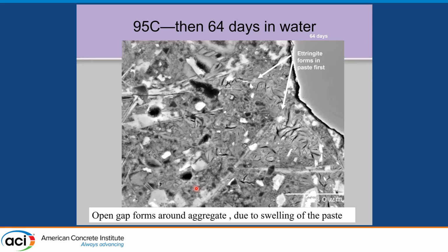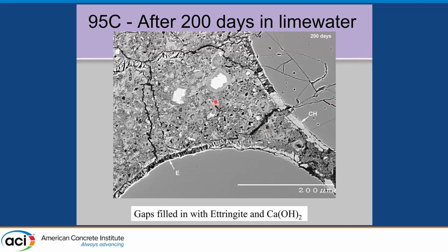And what happens then, when that sulfate comes out of the CSH, you start to form this delayed ettringite in very small spaces within the paste matrix. You see these little tiger stripe pattern things are ettringite that's formed in the paste. The other thing you notice here is this is a sand grain in the upper right, that the gap there is empty. So when the expansion occurs, the paste is expanding away from the aggregate and creating gaps around the aggregate. And then over time, CSH doesn't like to be in, or any crystals don't like to be in small spaces, so that ettringite redissolves and reforms into the interfacial transition zones.